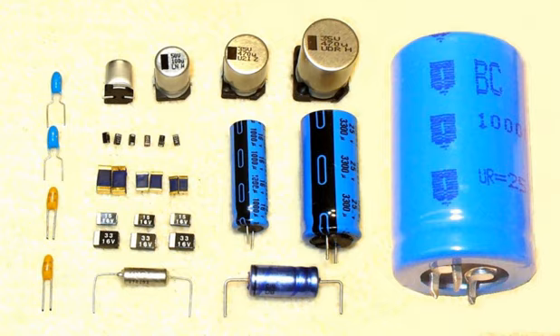The lifetime, service life, load life or useful life of electrolytic capacitors is a special characteristic of non-solid aluminum electrolytic capacitors, whose liquid electrolyte can evaporate over time. Lowering the electrolyte level influences the electrical parameters of the capacitors. The capacitance decreases and the impedance and ESR increase with decreasing amounts of electrolyte. This very slow electrolyte drying out depends on the temperature, the applied ripple current load, and the applied voltage.